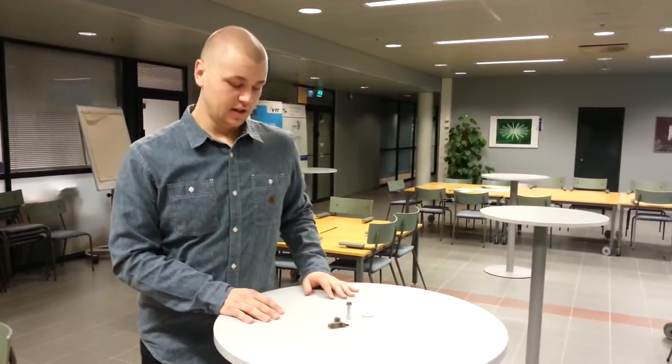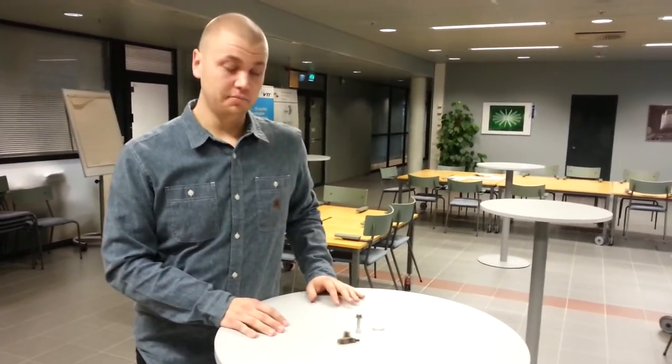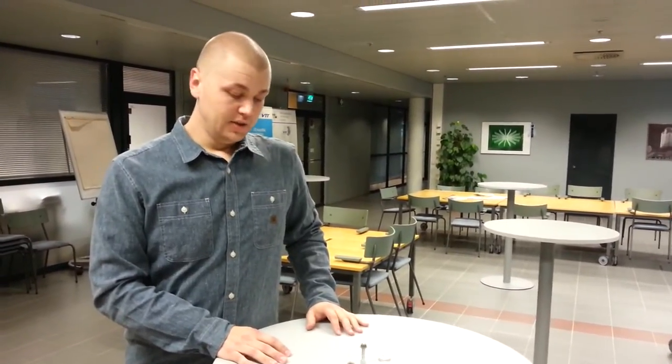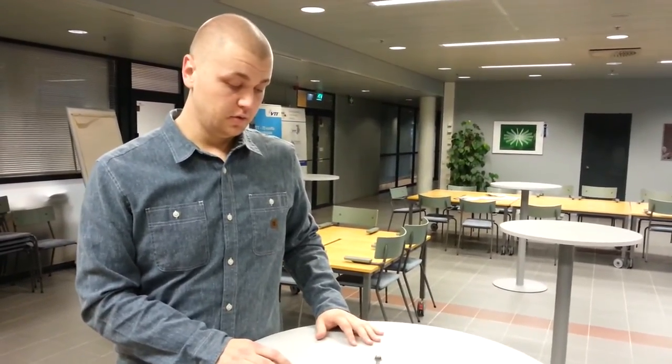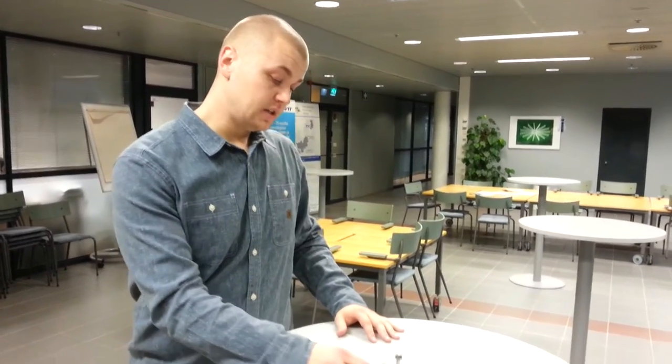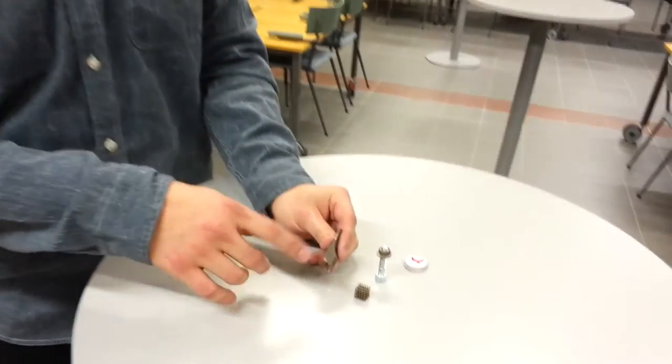When Gianmario presented the idea about making the fuel cells out of additive manufacturing, of course, we were thrilled and excited of trying to do it. And I'm going to tell a little bit about the technique itself. So basically, it needs a 3D model made with a computer program. And the 3D model is then prepared for the additive manufacturing machine by slicing it into the layer size. In our case, 20 micrometers. And the parts are built from the bottom to top, layer by layer.